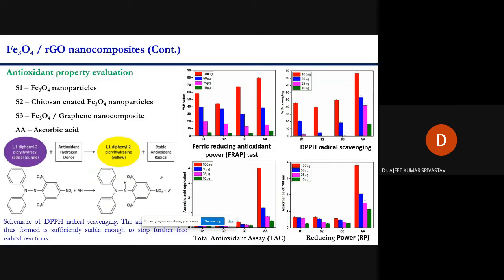Fine. And then we went for the antioxidant property evaluation. Here we have three types of material. One is without any functionalization, one is chitosan coated iron magnetite nanoparticles, and another is where we made the graphene and magnetite nanoparticle composites. In this antioxidant property evaluation, we showed that the functionalization definitely improves the antioxidant property of the bare magnetite nanoparticles. And ascorbic acid was used as a reference to compare the results.